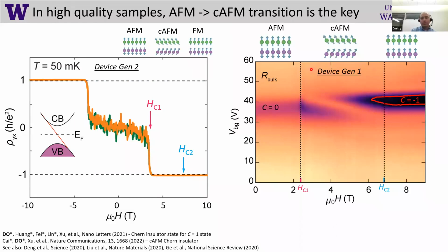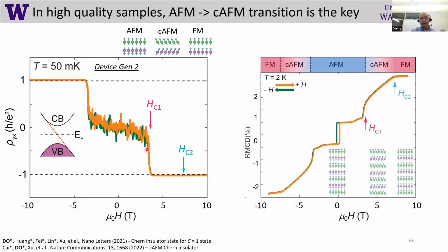So if we compare it with device generation 1, in this case, probably disorder, defects, things like that caused this transition to be more smeared. Essentially, it's broader as a function of magnetic field. In higher quality devices, we can get a sharp transition. And we can essentially check ourselves by checking magnetic state, in this case with RMCD, and we know exactly that this position when sample becomes quantized corresponds to this position when transition from antiferromagnetic to canted antiferromagnetic state happens. I just wanted to show at least once this data of RMCD.